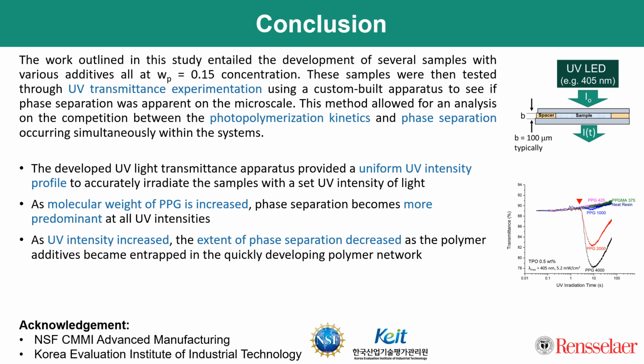We were able to conclude several things. Firstly, as the molecular weight of PPG increased, the phase separation in the system became more predominant at all UV intensities. And then lastly, as the UV intensity increased, the extent of phase separation decreased as the polymer additive molecules that were in the system became entrapped in that quickly developing polymer network.